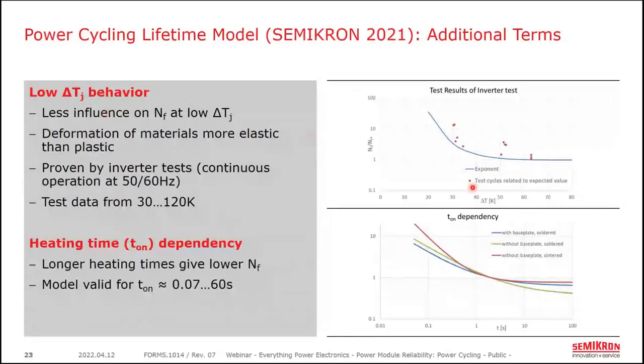So the new power cycling model downplays that influence of low delta T's at the lower temperatures. You can see here below 40 Kelvin or so, the number of cycles to failure starts to increase. And somewhat related to that is the effect of heating time, since higher frequencies also have shorter heating times. Tests have shown that longer heating times give lower number of cycles to failure, as well as changing the failure mode from purely bond wire failures to more chip solder and base plate solder failure modes, and what we call somewhat long power cycling. The model we have here has been validated with our test data up to heating times of about 1 minute.